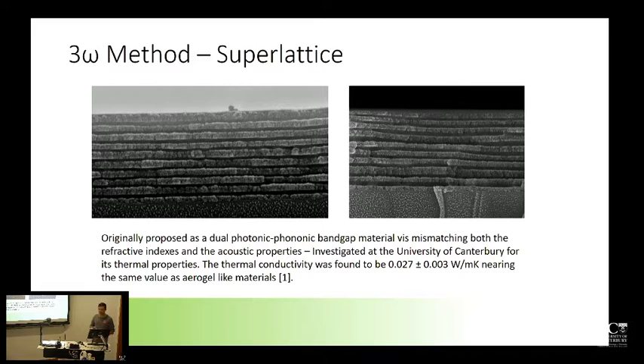In the past, literature has measured these structures to have quite a substantial phononic bandgap. We wanted to see if there was a corresponding decrease in the thermal conductivity at room temperature of the structure. So we used the technique that I'm going to be talking about in a second to measure this, and we found that it actually had a pretty low, in the scale of things, thermal conductivity. It's just slightly above that of still dry air at room temperature, which is considered to be a pretty good standard for thermal conductivity. And this is pretty much equivalent to silica aerogel-based materials.